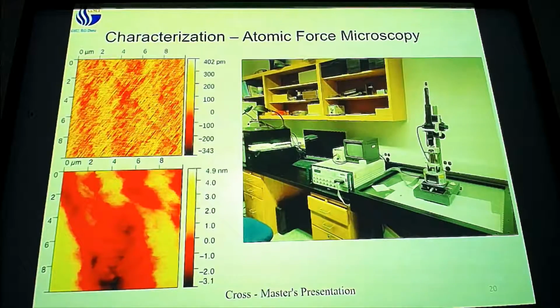These samples are sitting at, okay, the thickness question is a bit of a challenge. This is pure gallium nitride from the bottom up. So the layer that we grew on top, is that what you're asking? No, let me explain it. Sure. The layers, the overgrowth. Yes. So the layer we grew, both of these layers are grown upon gallium nitride that is on top of the substrate. So this here is gallium nitride on gallium nitride. This one is gallium nitride on sapphire.